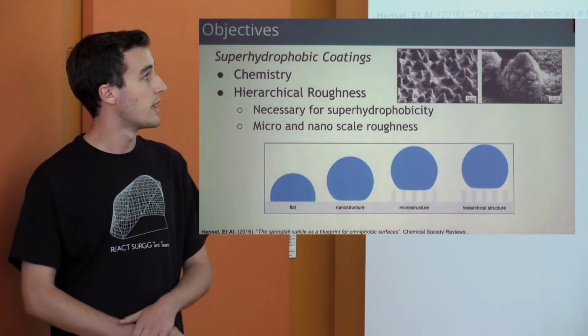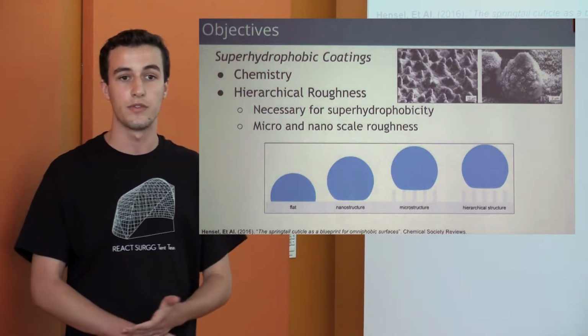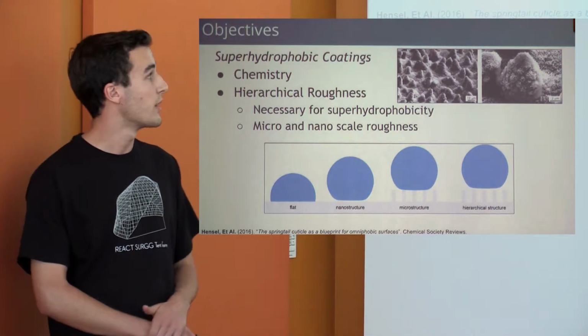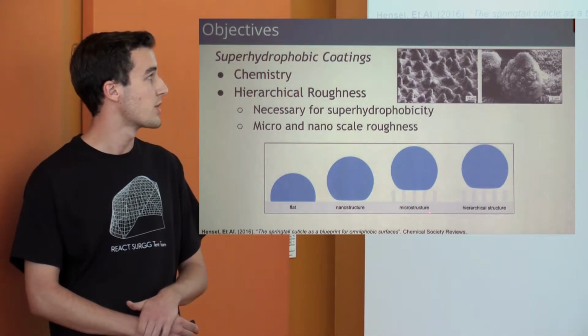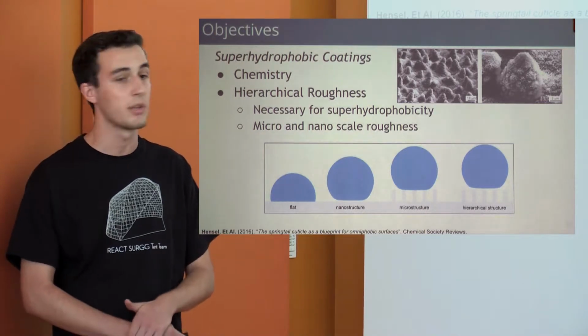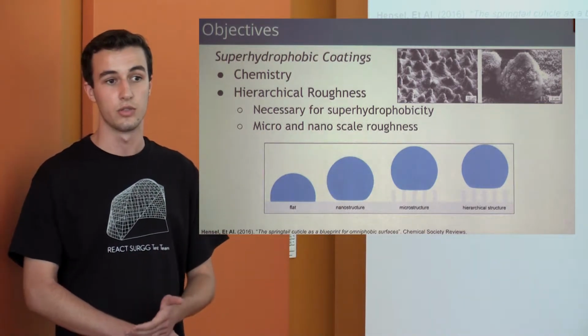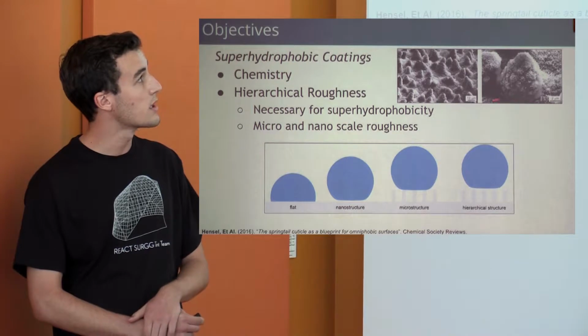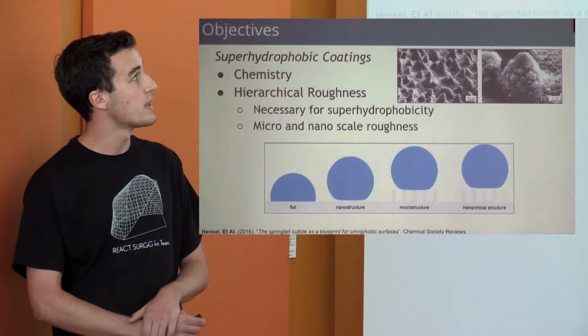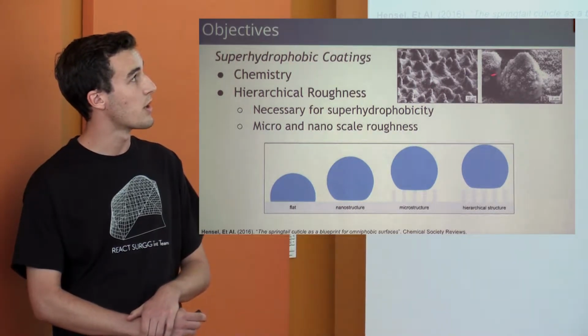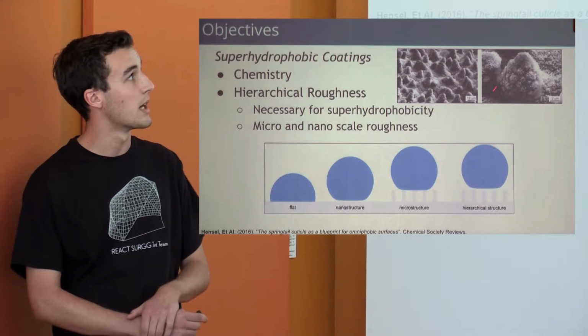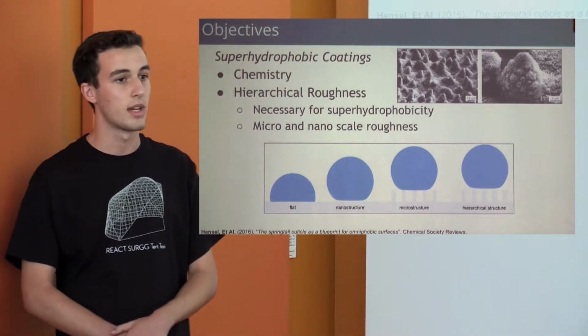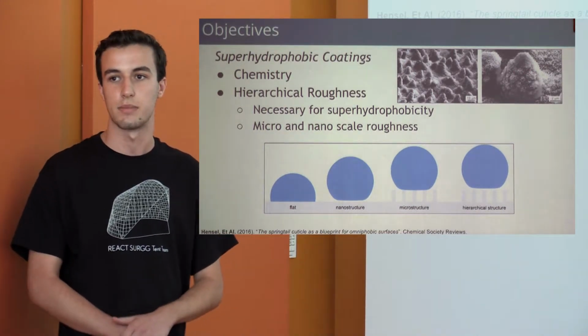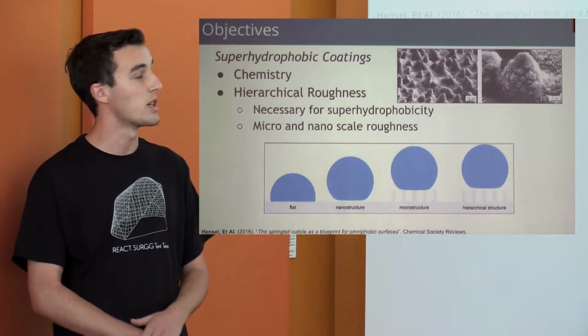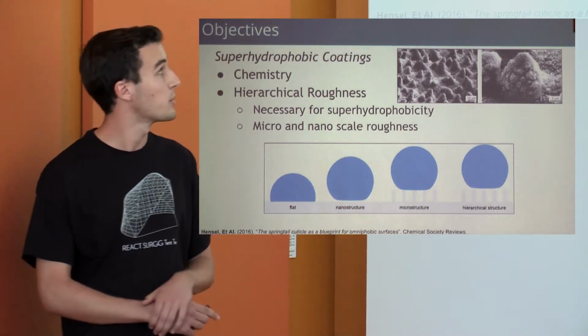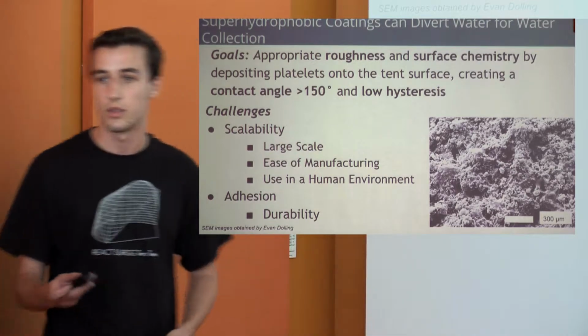We also found out that to achieve a superhydrophobic surface, you need not only micron-sized structures or nanostructures, but a combination of both for a hierarchical roughness. This is what the lotus leaf is able to do, where you can see it has the micron-sized structures, but also the nanostructures on top of each little mound. That allows it to have as hydrophobic a surface as possible. So this is what we're trying to achieve with our coating. I'm going to pass it over to Kathryn, and we'll talk about the actual coating.